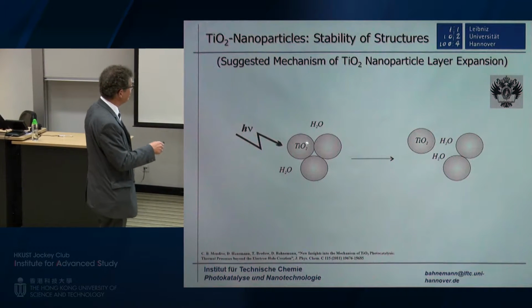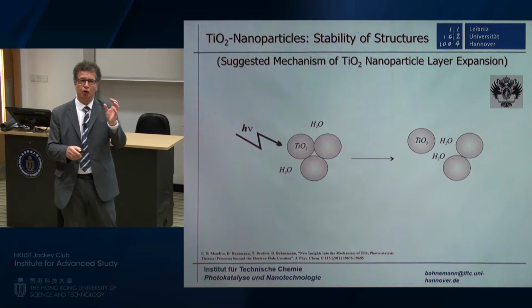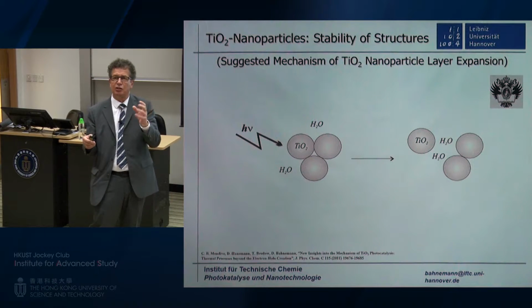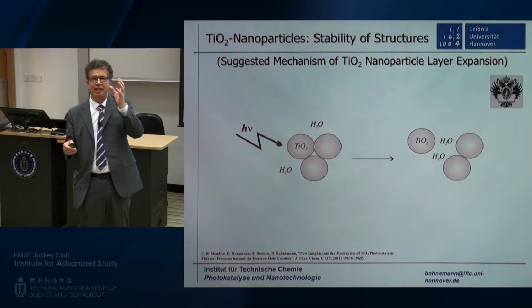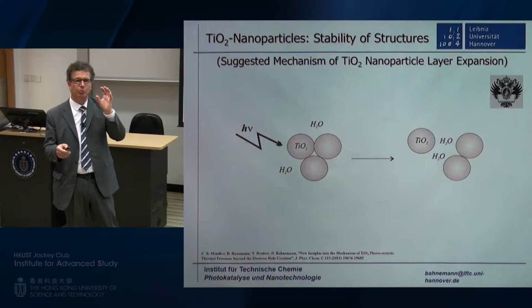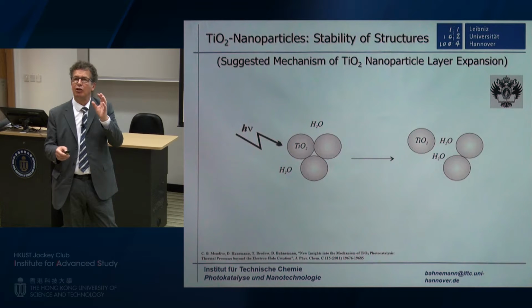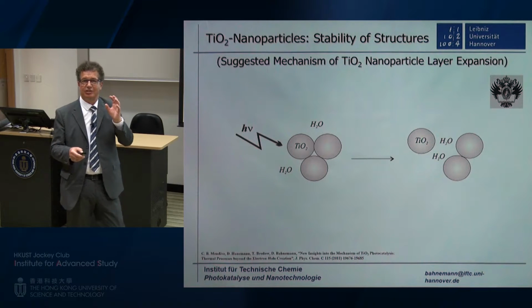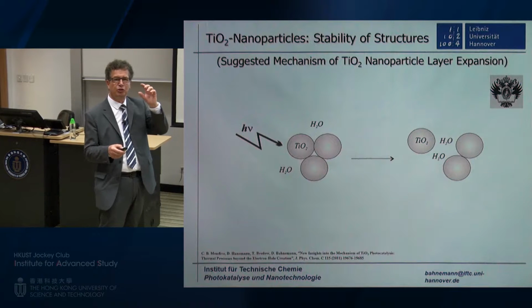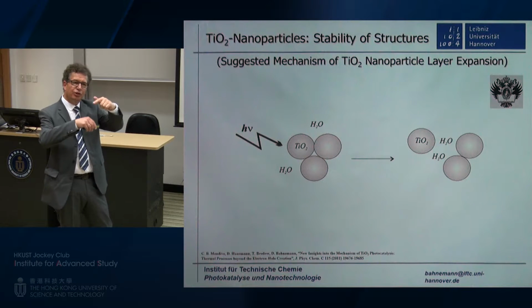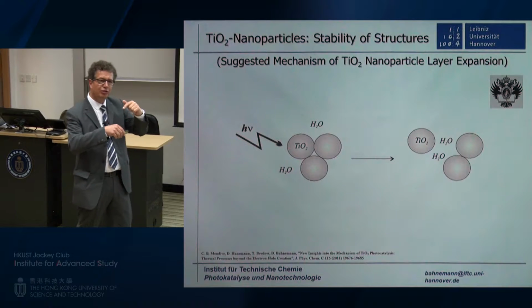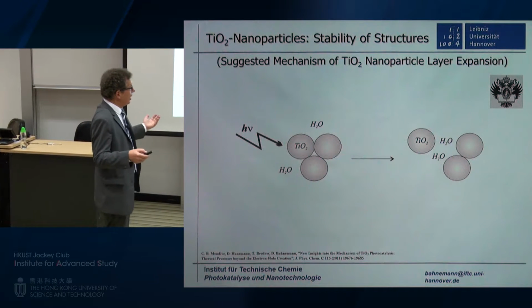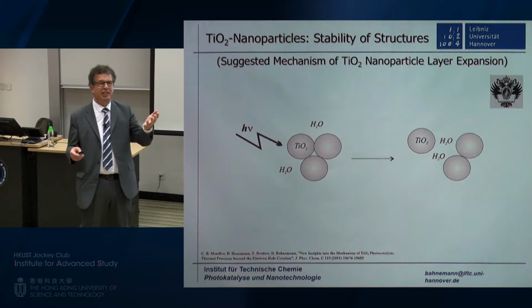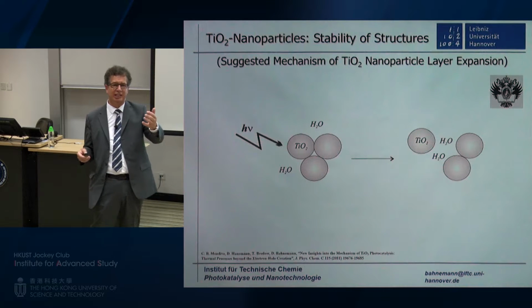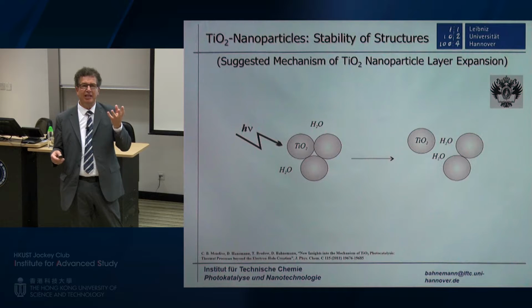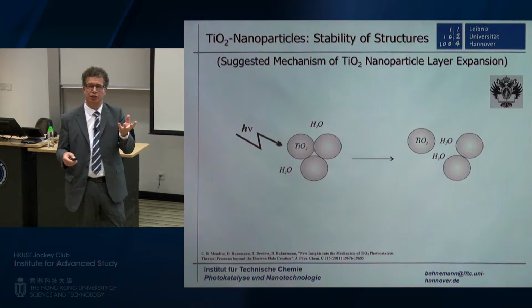Now you excite the nanoparticles, you form your electron hole pairs, and they have nothing to react with. So what can they do? Just recombine. You get an electron hole recombination, but this will liberate a lot of energy. The band gap of TiO2 is 3.2 electron volts, so each recombination of an electron and hole will liberate 3.2 electron volts. And how is this liberated? There is hardly any luminescence, so it's not liberated as light. It's mainly transformed into thermal energy.